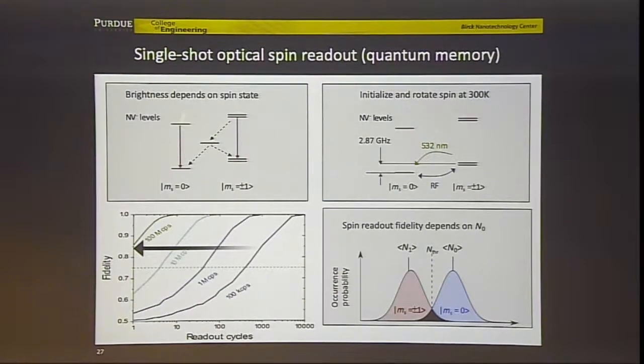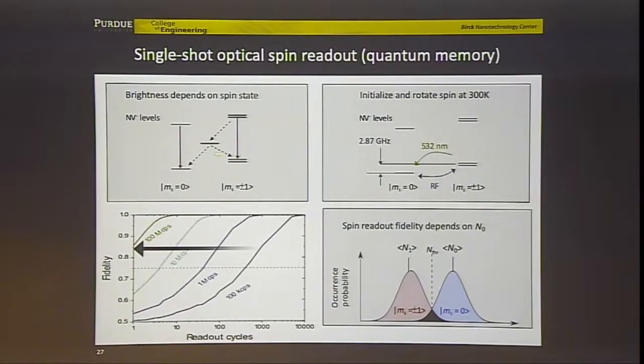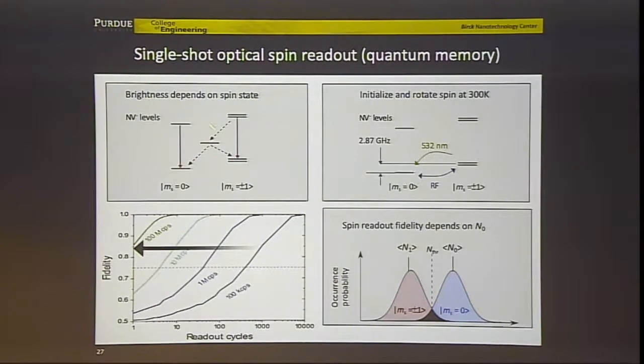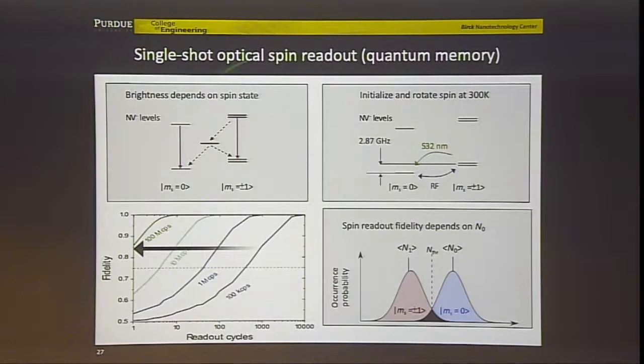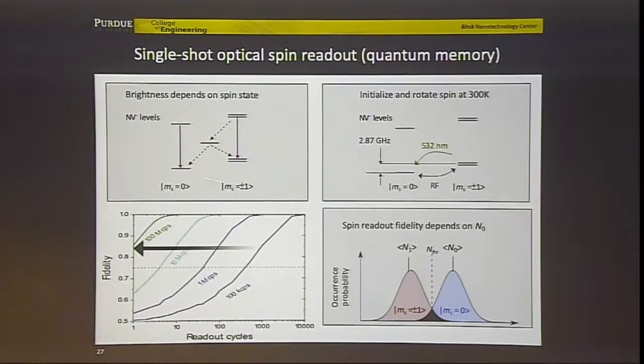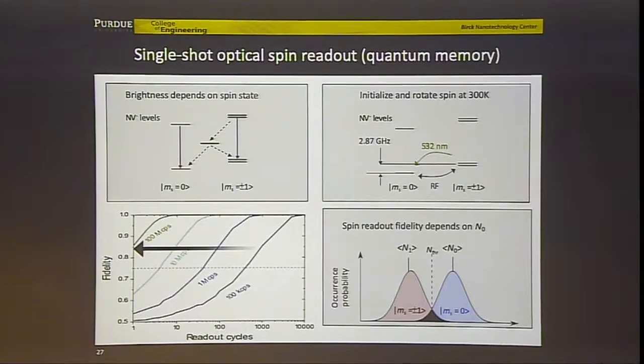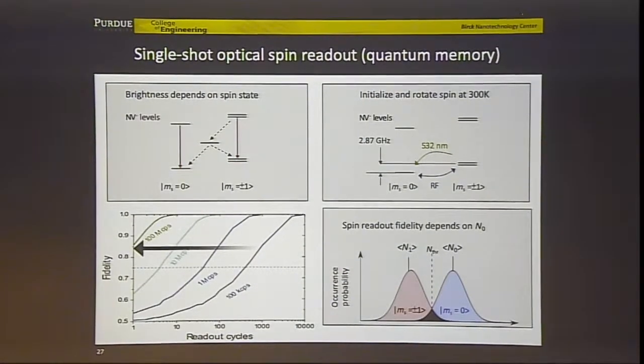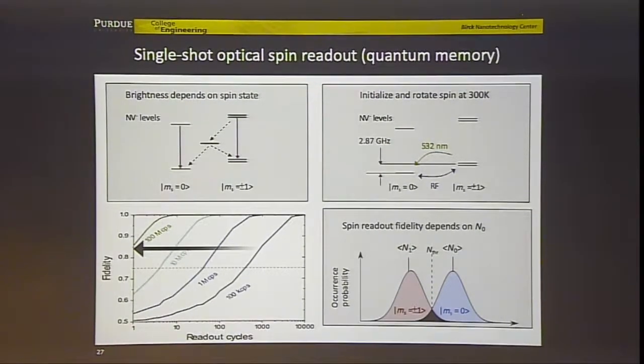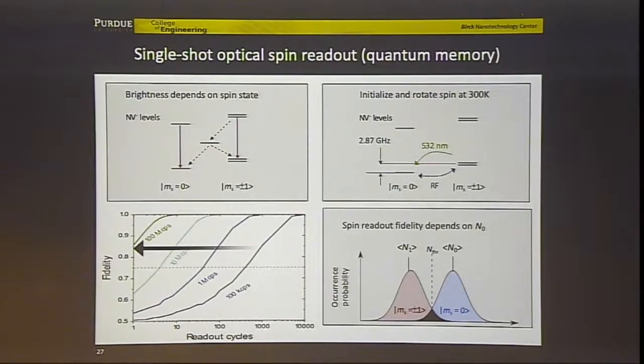But the trick with this is that you have to do it within a time shorter than the lifetime of this metastable state, which is 300 nanoseconds. Because if I do it too long, then eventually I move everything to the S equals 0 system. It's a metastable system. You have to do it fast. You would like to read your spin without changing the spin, so you have to do it within a time shorter than 300 nanoseconds. But the conventional rate of emission of single photons is 100 kilocounts per second. It means that within 300 nanoseconds, you have much fewer than one single photon.